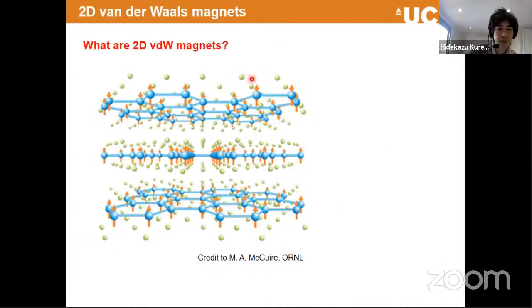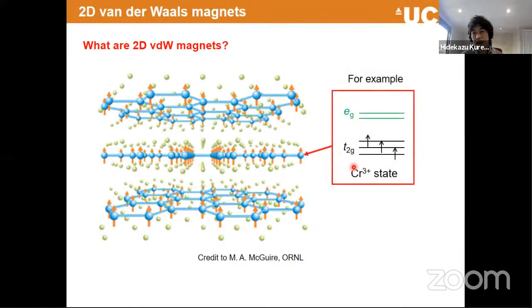All right, so this is just a cartoon to illustrate what a 2D van der Waals system looks like. It's nothing but a simple layered system. It has a van der Waals gap. And the difference between this and graphene, for example, is that it typically has 3D transition metal ions or elements, and it has a finite magnetic moment because of Hund's rule. A typical one is, for example, the chromium 3+ state, and it has some octahedral crystal field splitting. If you populate 3 electrons in this state, then we have 3 spin-polarized electrons in one band, the t2g band, and that can create a local magnetic moment.